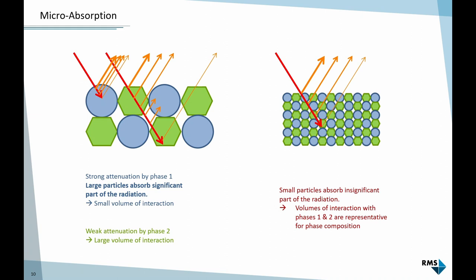It doesn't show as poor refinement. We just get a biased result, the wrong result, but the fit looks good. It's hard to track once you don't get the quantities you expect. You'd have to look at the sample in the SEM, for example, and check or measure the particle size in the state you used for XRD analysis after milling. Make sure with your sample preparation routine that you get fine powders, typically below 5 microns, between 1 and 5 microns.